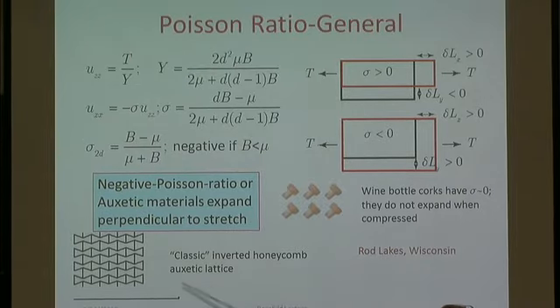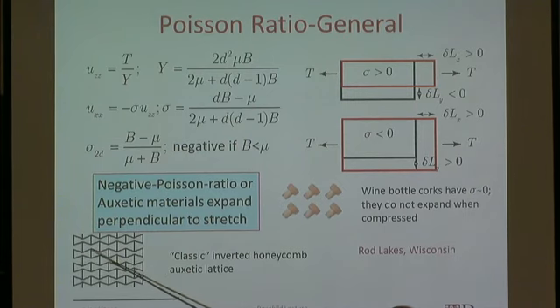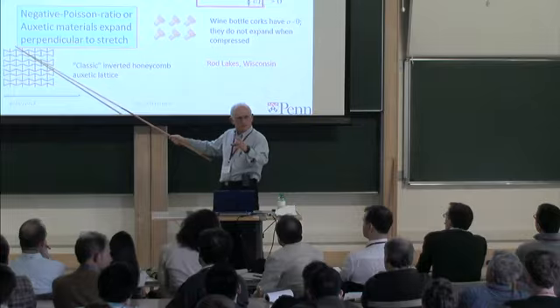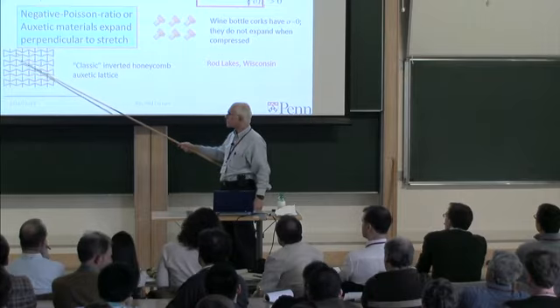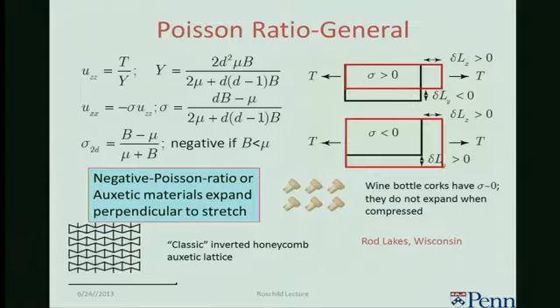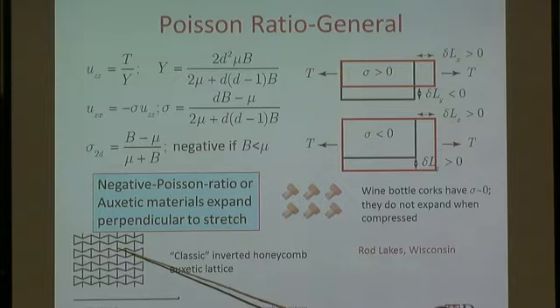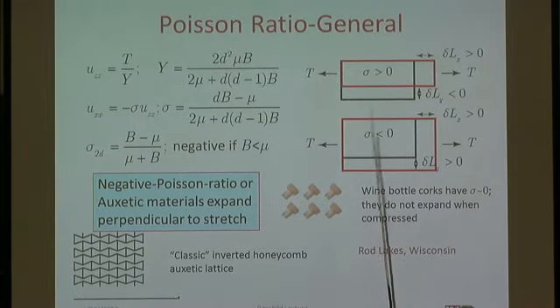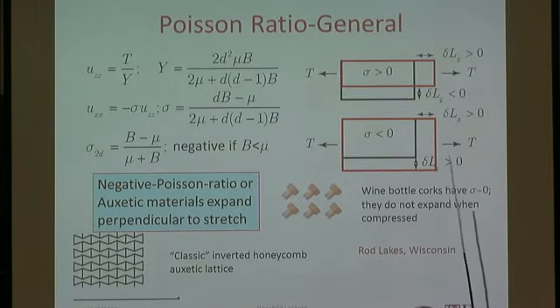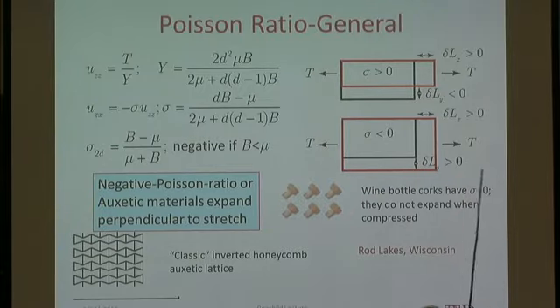And the classic example of an auxetic system is the inverted honeycomb lattice, which is right here. If you look at this bow tie in the middle and you expanded it out so this was on that side and that was on the other side, you would have a lattice of hexagonal cells, which is the honeycomb lattice. And obviously, if you pull this one out like that, it will tend to push this way and that way, and you get an expansion in the other direction. So, you know, the world's expert on this is Rod Lakes at Wisconsin, and he's actually made a three-dimensional auxetic foam by starting with a foam, compressing it, and then cross-linking it in such a way that you lock in the three-dimensional version of these things, and it's actually isotropic.